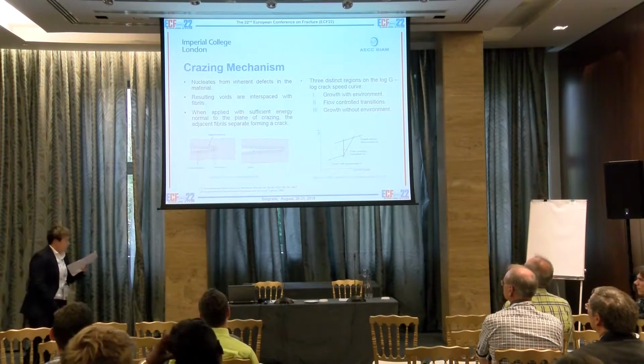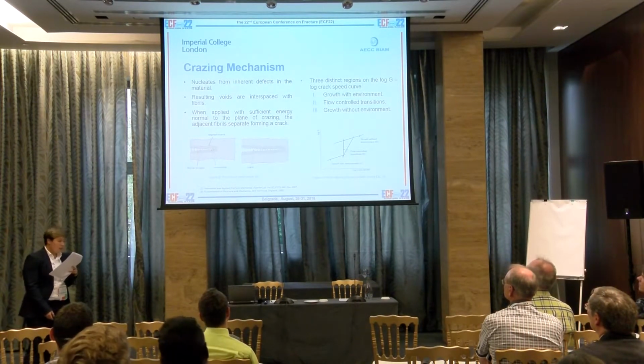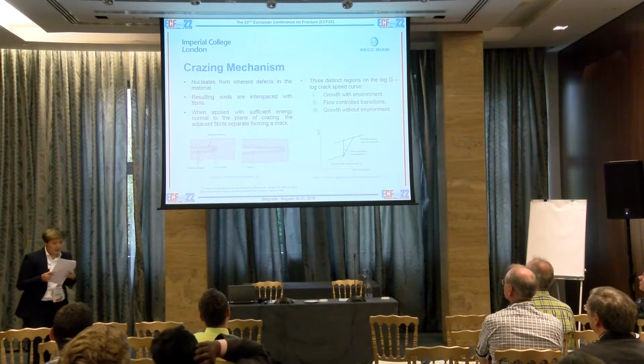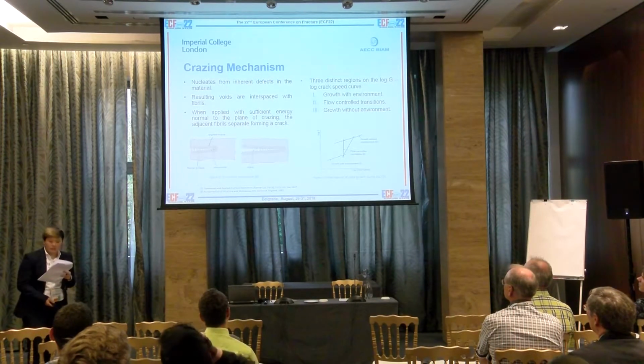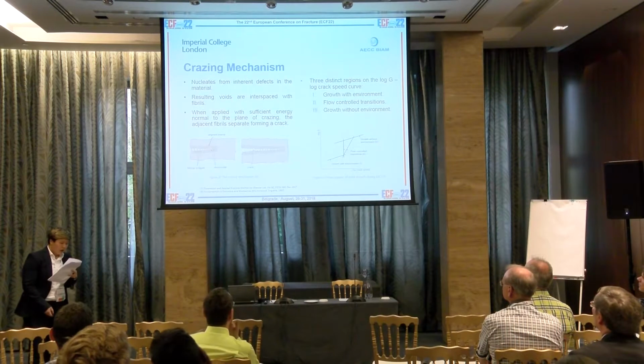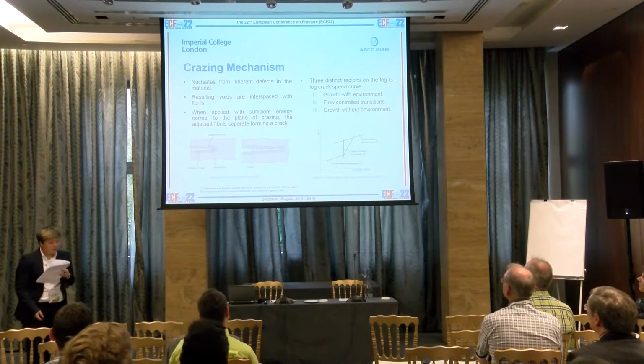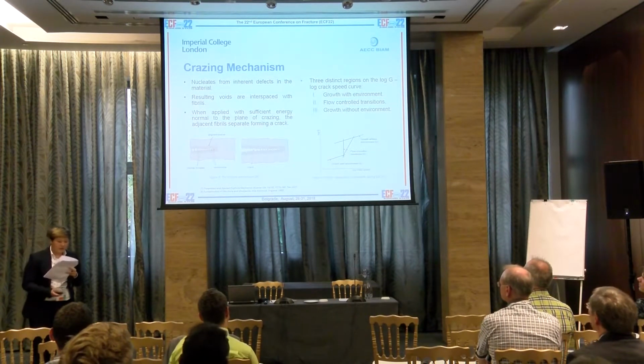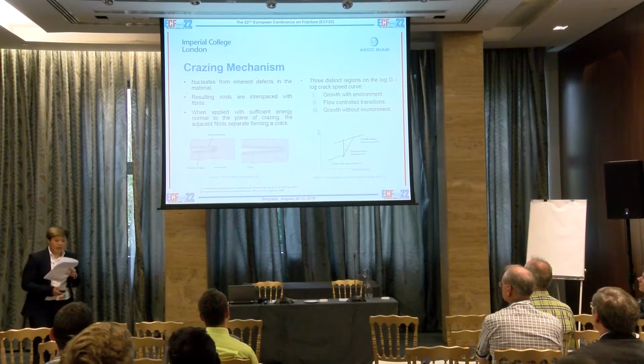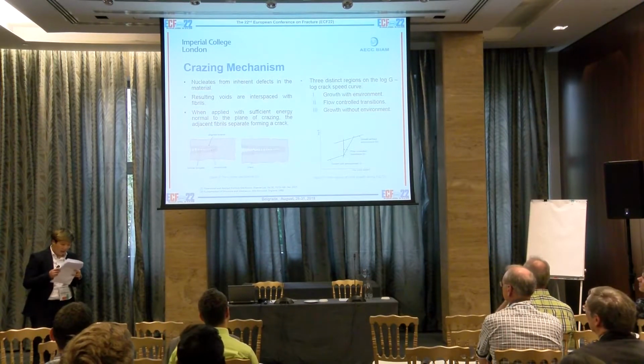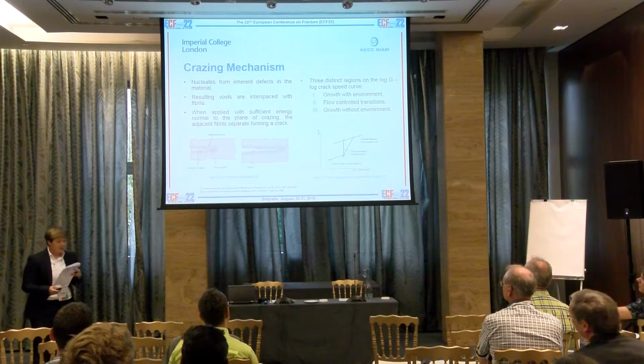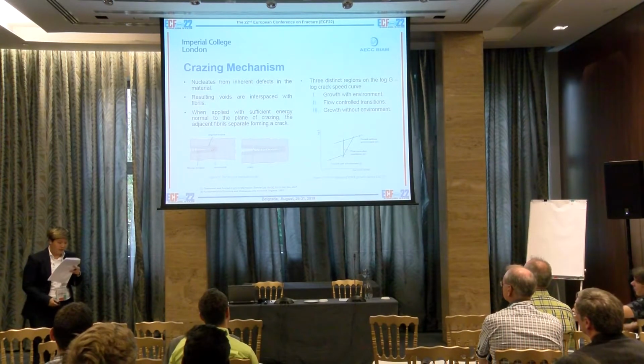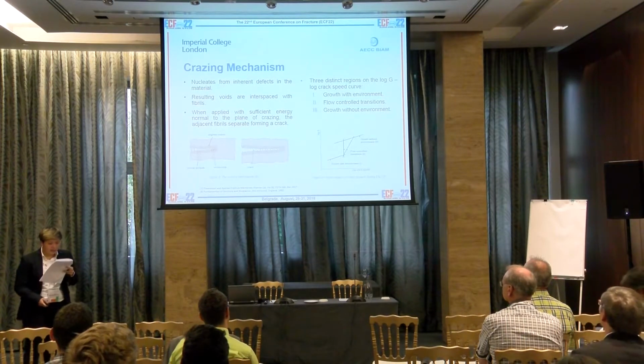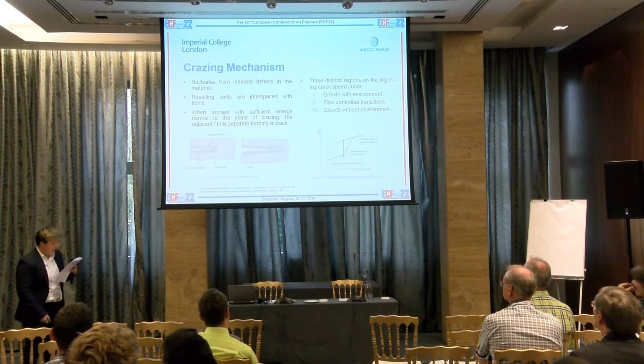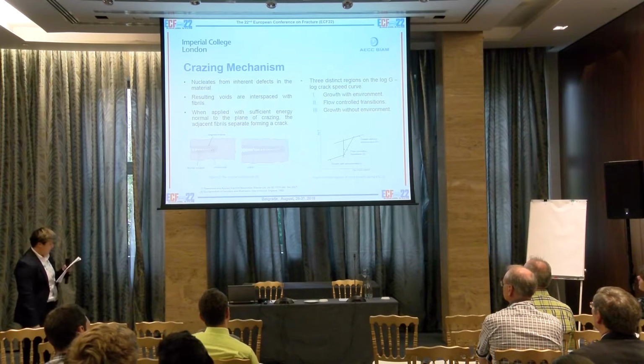The crazing mechanism. Crazing often nucleates from inherent defects in the material, resulting in voids interspersed with fibrils. When applied with sufficient energy normal to the plane of crazing, the adjacent fibrils separate, forming a crack. The fracture process experienced in ESC can be explained by the relaxation growth model.